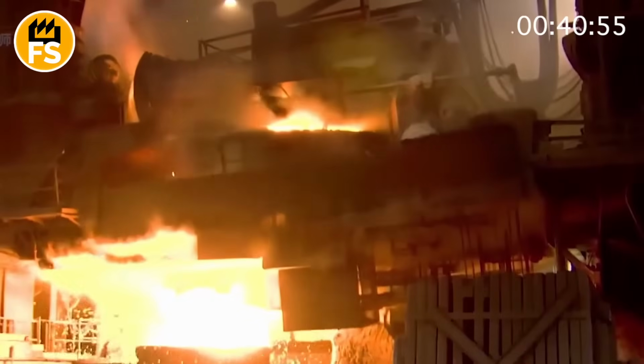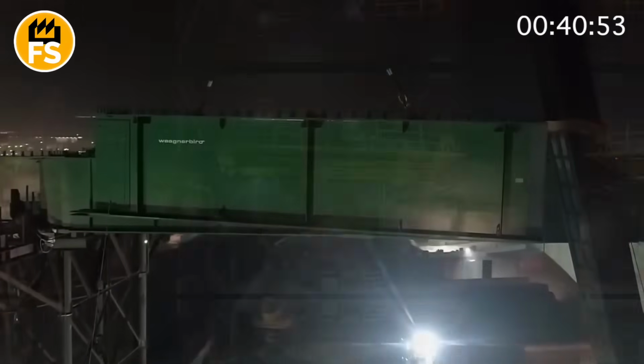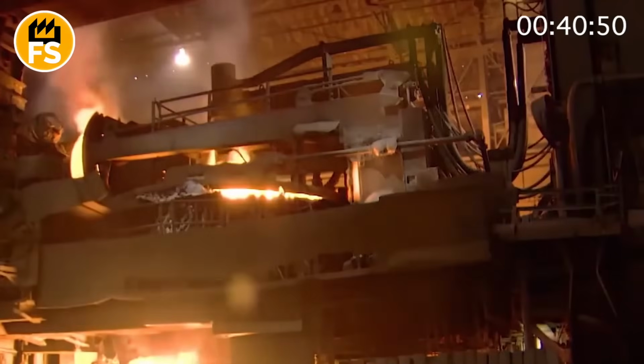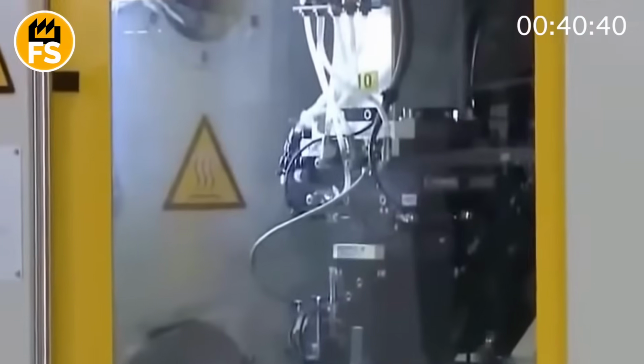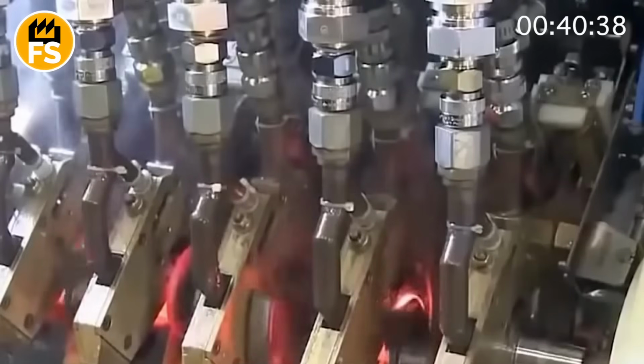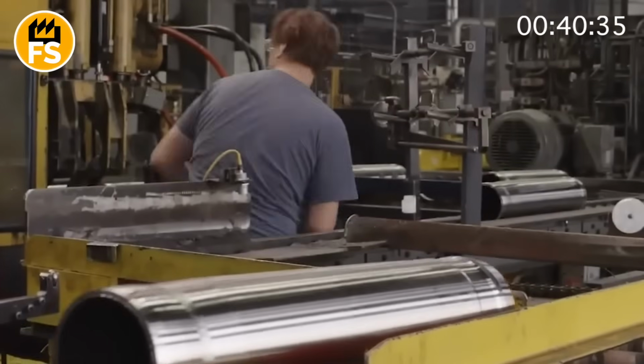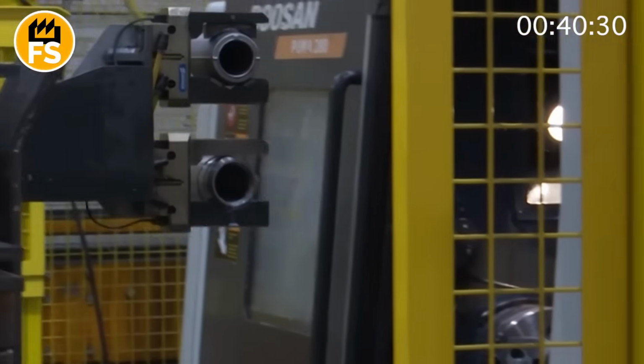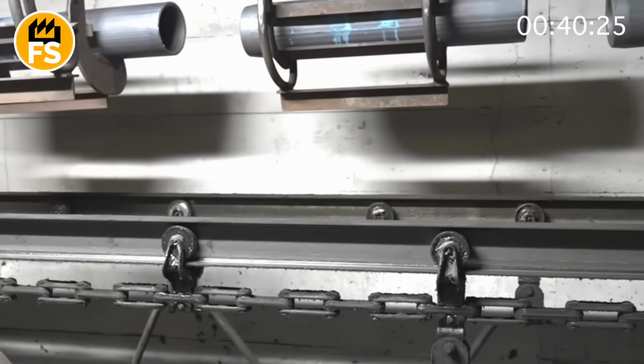The blanks are submerged in furnaces where the temperature reaches over 1,600 degrees Fahrenheit. In a dark hall filled with the orange glow of the metal, giant furnaces heat the casings to a state where the steel becomes more flexible, loses stress, and acquires the necessary strength. After heating, rapid cooling. This is either an oil bath, streams of air, or water quenching. The choice depends on the type of alloy. The process is called hardening, and it's what transforms the shell casing from a simple blank into steel capable of withstanding the immense stress during firing.